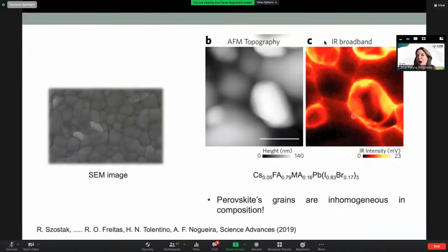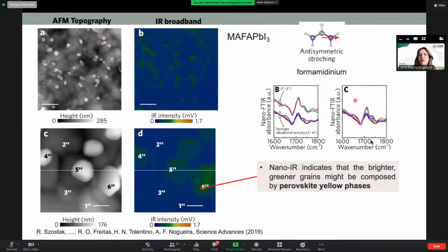What happens in these regions that are very close to the grain boundaries means that we have some lack of formamidinium in these regions here, and how can we play with the composition in order to minimize this. But what was interesting for us was also to get the point spectrum. We chose many grains in the perovskite here, especially these greener grains, and took some infrared spectrum. This peak here at 1700 corresponds to the asymmetric stretching of the formamidinium. And we are able to identify those grains as the yellow phase.